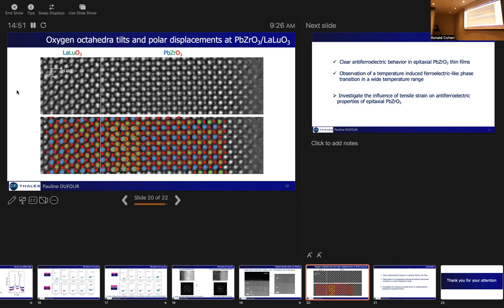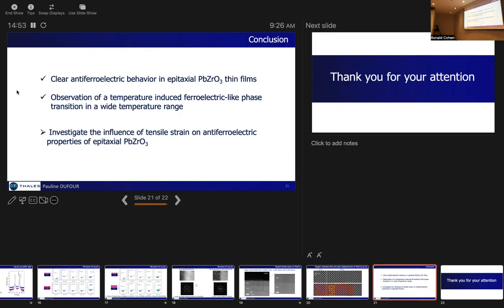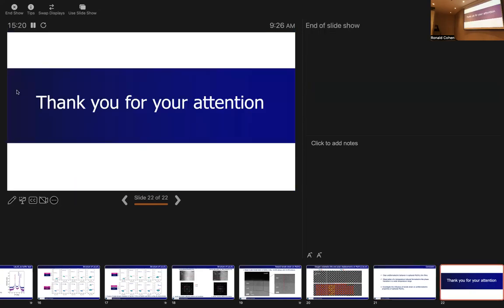So to summarize, we have elaborated antiferroelectric thin films of 45 nanometers. We could see that we have an intermediate electric phase that is induced by temperature, whose polar structure as well as the polar structure of the electric field induced phase transition remains unclear. And finally, we have developed these bilayers to induce tensile strain in lead zirconate, which require further investigations. So thank you for your attention.